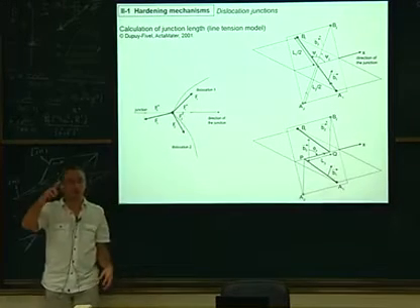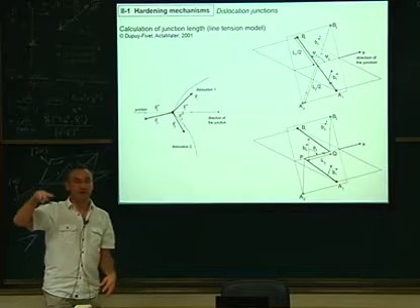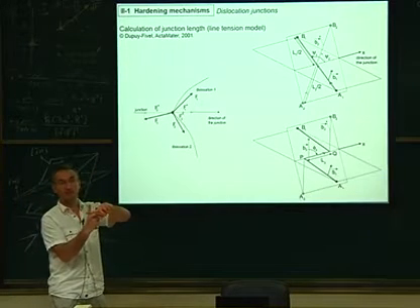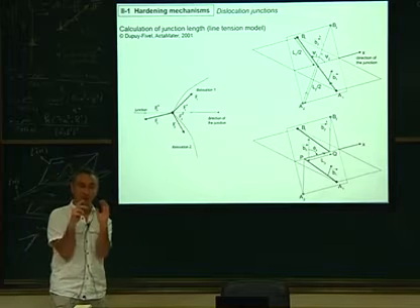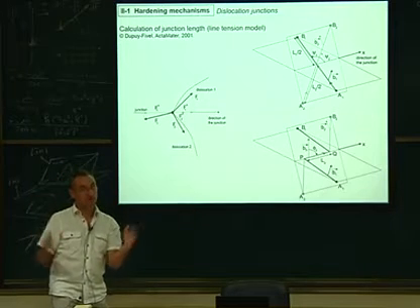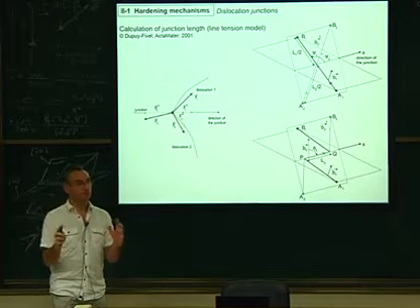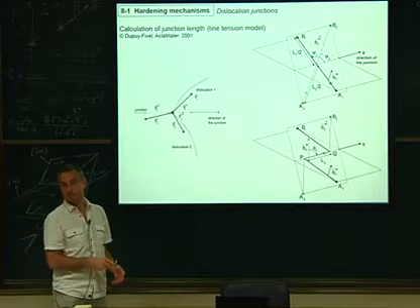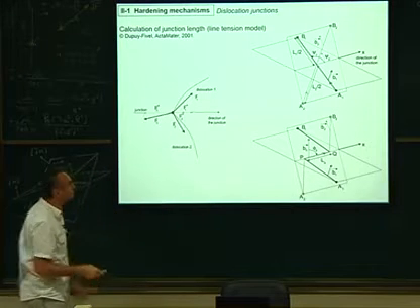We are comparing mu b1 squared plus mu b2 squared, when the two lines are separated, versus the fact that they merge, so mu (b1 plus b2) squared. If (b1 plus b2) squared is lower, then the dislocation will move and create a junction. That's the analysis, more or less, this is what we put.